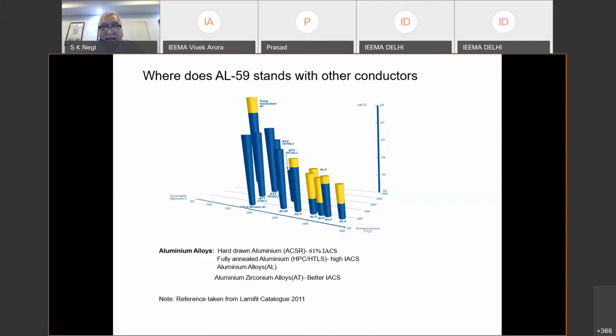So from this we see that AL59 conductor can stand up to 95 degrees centigrade, having a conductivity of 59%, and a better capability of standing temperature as well as lesser sag than ACSR Moose conductor. And when I put on the chart this ACSR Moose conductor versus AL59, here you can see that ACSR Moose at 85 degrees centigrade is carrying 794 amps. But this amperage is actually limited, as I said in the beginning, by surge impedance loading, particularly for a line which is more than 150 kilometers.